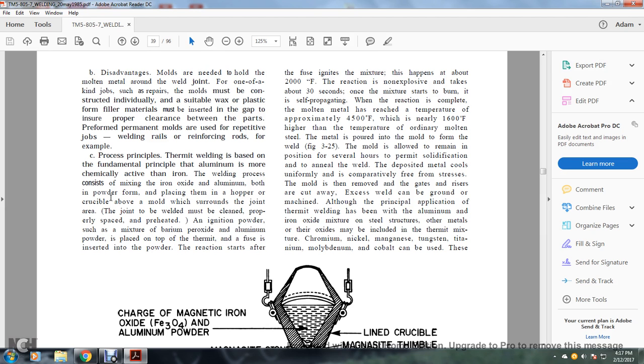Process principle. Thermite welding is based on the fundamental principle that aluminum is more chemically active than iron. The welding process consists of mixing iron oxide with aluminum, both in powder form, and placing them in the hopper or crucible above the mold, which surrounds the joint area. The joint of the weld must be cleaned, properly spaced, and preheated. An ignition powder, such as a mixture of barium peroxide and aluminum powder, is placed on top of the thermite, a fuse is inserted in the powder, and the reaction starts.